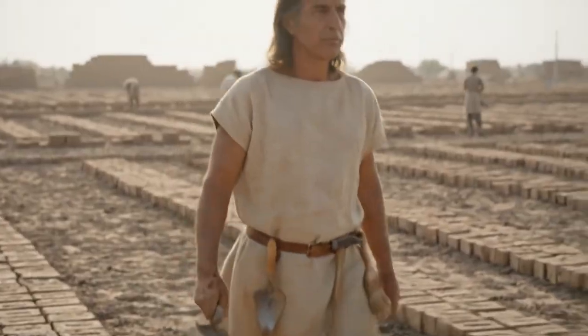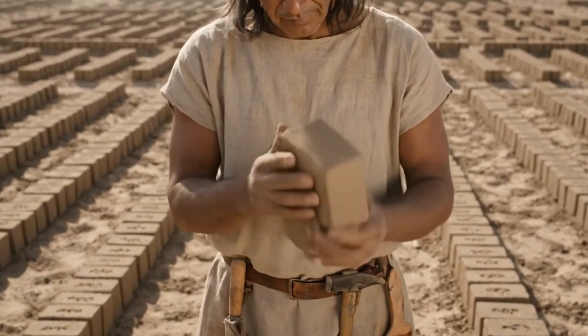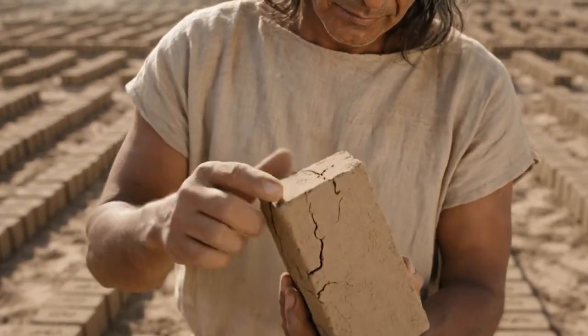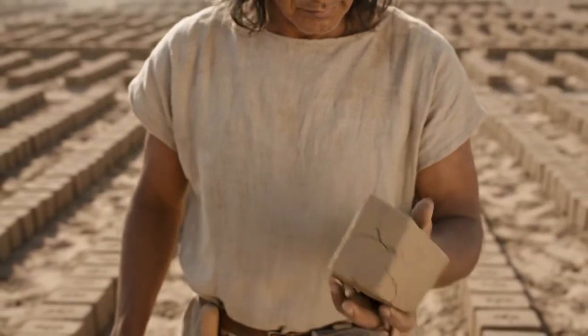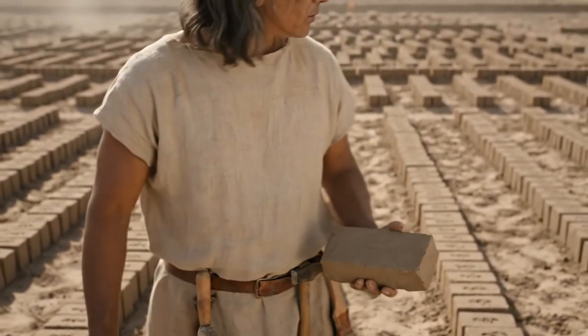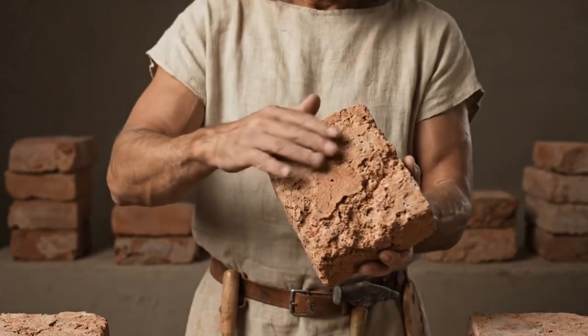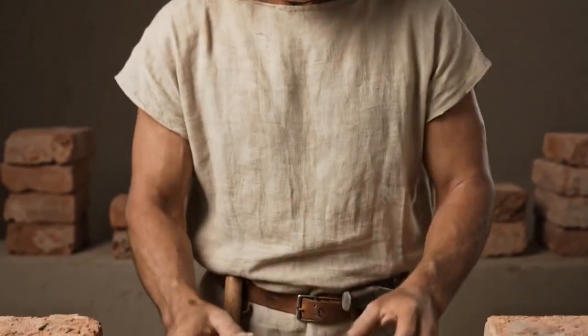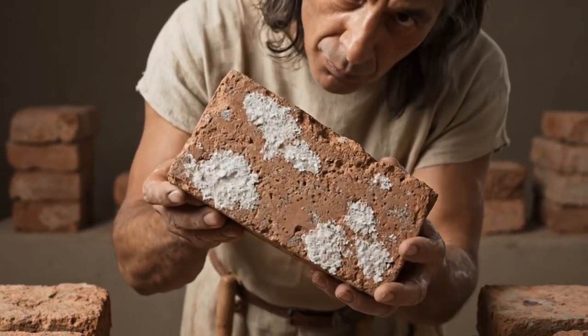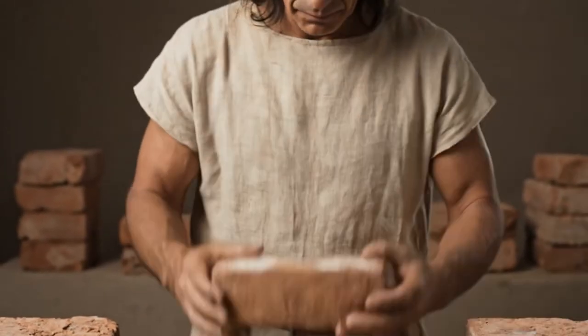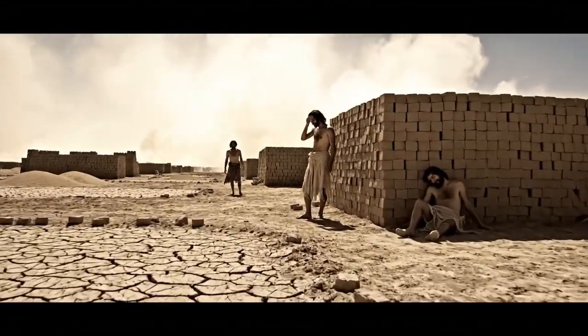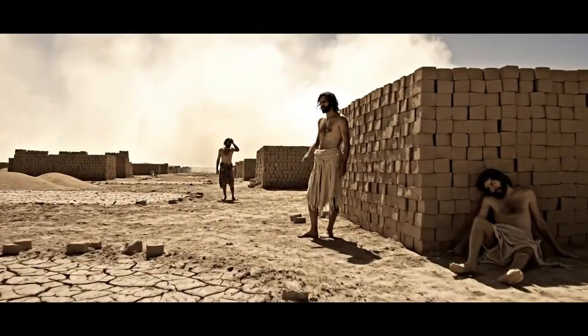The master brickmaker is walking through the drying field constantly, checking bricks at different stages, looking for the telltale signs of problems. Cracks forming at corners mean the clay is drying too fast. Sagging shapes mean the clay was too wet when molded. White patches on the surface mean salt is leaching out, and this batch of clay needs more washing.